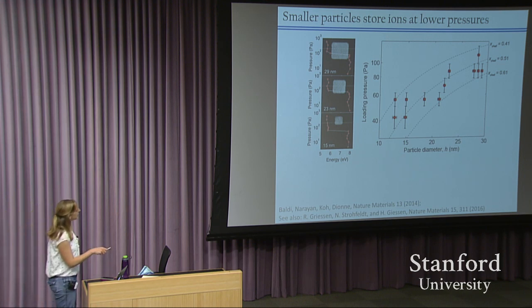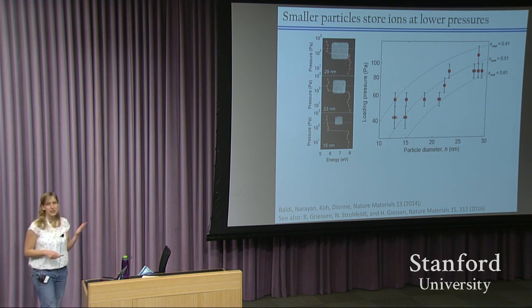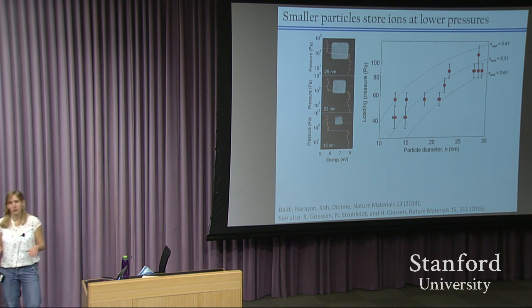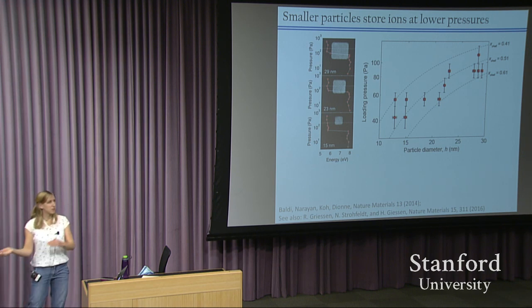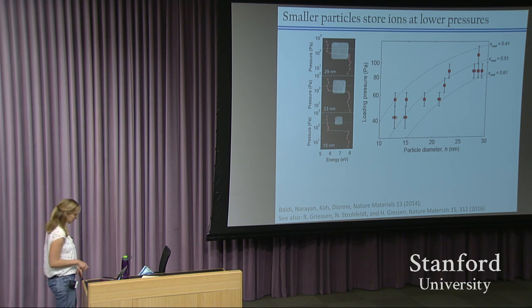And another trend we saw is that if you plot the loading pressure as a function of particle size, the smaller particles tended to load at lower pressures. So it's much easier to get the smaller particles into the beta phase, or basically they transition to the beta phase at lower hydrogen pressures.